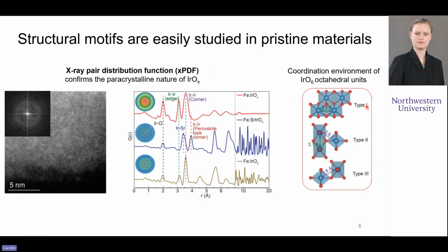This type 1 is just the set of edge-sharing octahedral units that repeat across. The type 2 connections are present in the rutile structures, which are a combination of edge and corner-sharing octahedra. And then the type 3 connections are corner-sharing octahedra only. And so now that we have a really good idea about what these pristine catalyst materials look like, we then need to figure out, okay, if we use those catalysts and we subject them to whatever transformations occur when they do water splitting, how do they transform?